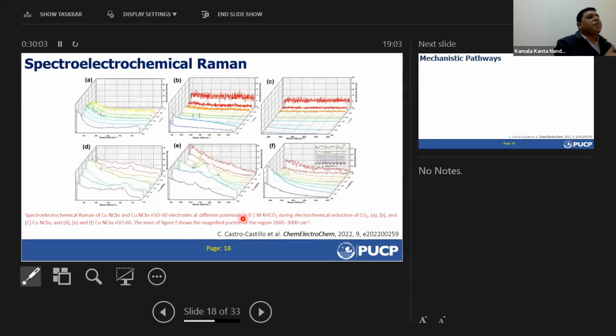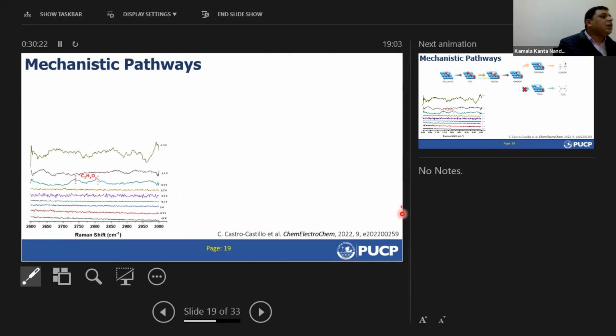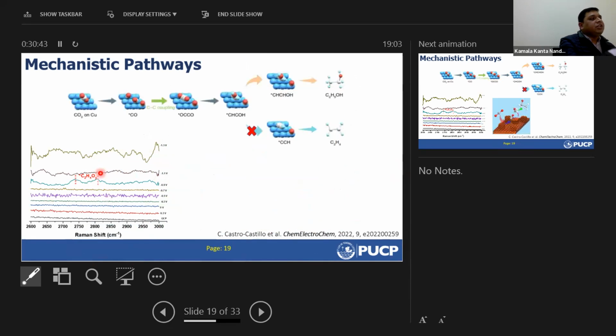So we did spectroelectrochemical Raman characterization to see why we are obtaining a higher amount of ethanol over ethylene, and which species is responsible. We find the difference is in this region of the spectrum. We recorded this Raman spectrum by applying the potential and monitoring the formation of the intermediates, and you can see that at minus 0.9 volt, this intermediate is forming. This is the potential where we are getting a higher amount of ethanol. Then, when we looked at the DFT calculations in the literature, we found that this corresponds to this kind of intermediate.